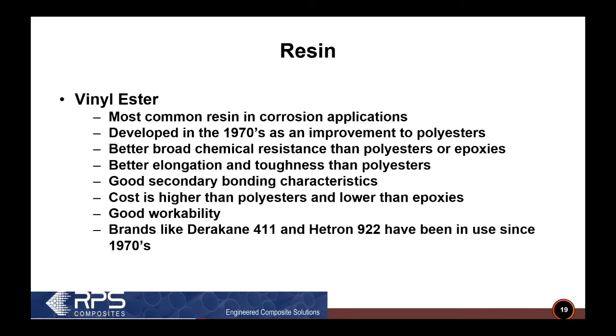Vinyl esters, which have actually been around for over 50 years, are the most commonly used resins in corrosion applications. What a vinyl ester is, it's actually called epoxy vinyl ester because it's a polyester resin that has an epoxy backbone. And what that does is the epoxy backbone gives the polyester resin the characteristics of an epoxy. So the secondary bonding characteristics and the elongation is better, closer to an epoxy. But the corrosion resistance is more like a polyester.